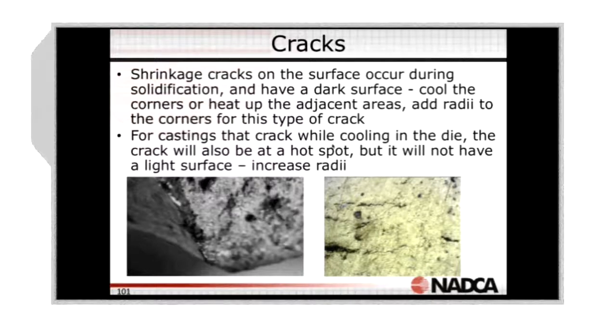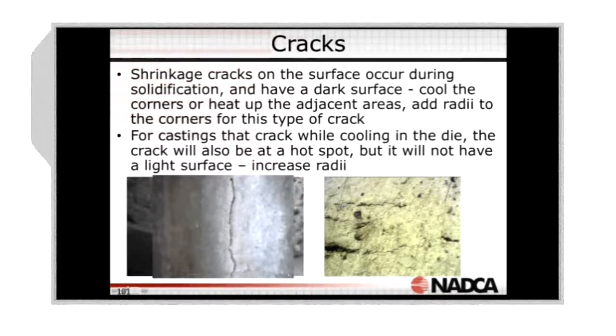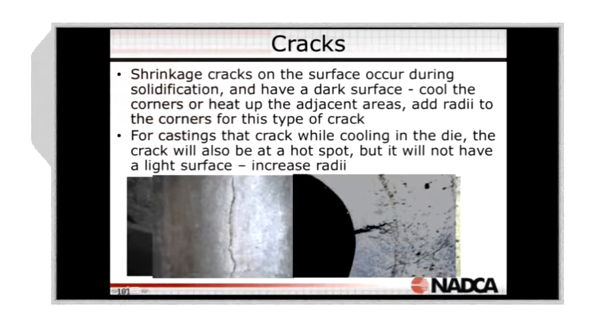If we look at a typical hot crack, it looks like that. They're usually not long, but they're wide — the distance between the two faces. And if you cut it and polish it, you see that. The crack is not deep, but it is wide on the surface, which means it cracked while it was hot. So this area is most probably a hot area — and if it's hot, cool it. If it's cold, warm it.